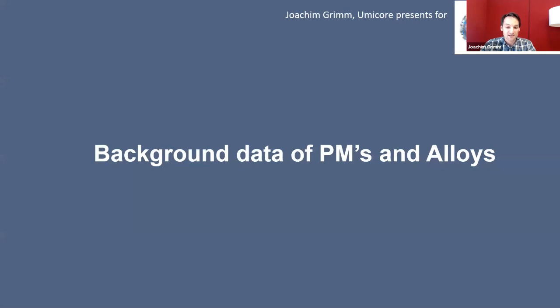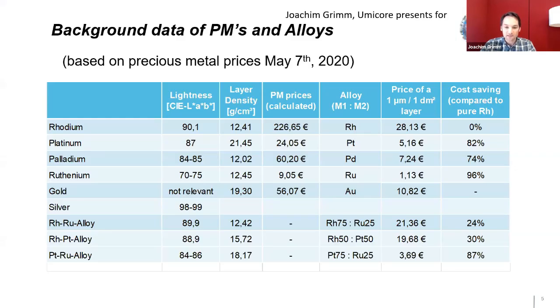I want to go to the background data of the precious metals and their alloys, because here the main figures are hidden. The point is the very high pricing of pure rhodium, which has a very wide and light shine if you plate it on jewellery, but on the other hand, you have the highest price if you buy it at the precious metal pricing on the market. If you do a pure plating, this calculation shows the price of 1 micron on 1 square dm layer is about 28.13 euro. But of course, the jewellery industry mainly needs this rhodium for a wide, hard, abrasion-resistant layer.